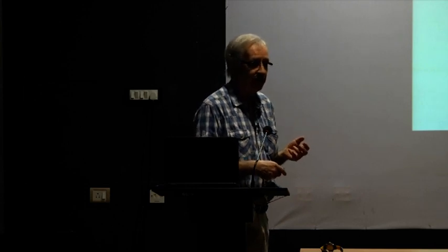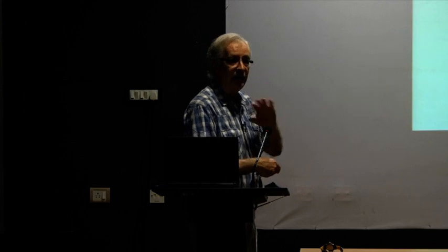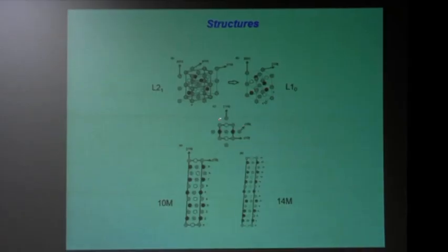And how do we visualize the modulation? So basically, everything is tetragonal. So if we look at this and come over here, let's take a look at this cell over here. So this is more or less identical to this. So we have one of these here. But it's a little off. So it goes 1, 2, 3 in this direction and 3 in this direction. And this was known as the 10M. Today it's known as the 5M. Okay? So you go 1, 2, 3, 4, 5, and then 1, 2, 3, 4, 5 to be able to repeat this structure over here.